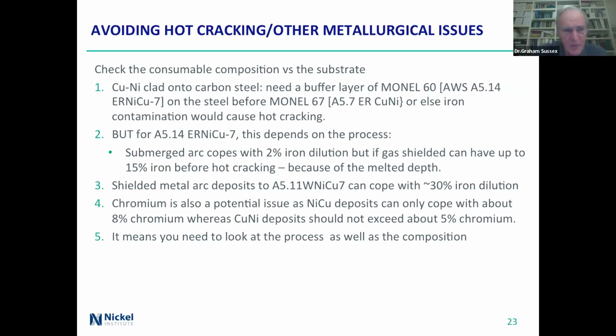If you're looking at shielded metal arc deposits, they can cope with about 30% iron dilution. That's pretty dramatic. And for chromium, nickel copper deposits only cope with about 8%, whereas copper nickel deposits shouldn't exceed 5%. It really means you need to look at the process as well as the composition.